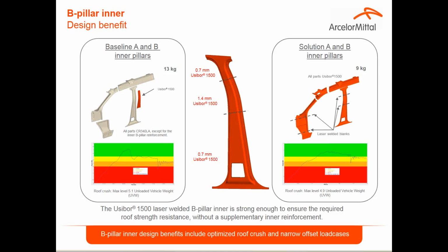Several times we need patches for both reasons, stiffness and crash. Laser welded blank is well applied and it works well for cost and weight when we integrate some parts together. And this is a good example in which the patch has been integrated in the inner B pillar by modifying just the thickness and maintaining the same grade. This case, if you see on the bottom, helped to improve the roof crush case.